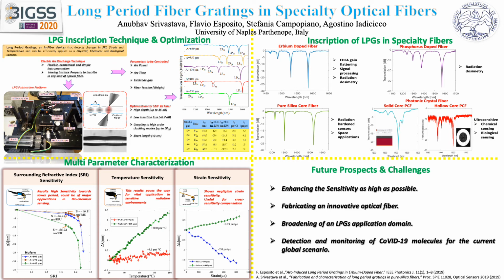Likewise, in temperature, you can see for photonic crystal fiber it is almost negligible, very little sensitivity, around plus 4.6 picometer, and for Nufern it is quite considerable, a significant sensitivity of around plus 30.0 picometer per degree Celsius. In strain, you can see it shows more or less negligible strain sensitivity, but it is very useful for cross sensitivity compensation. For Nufern around 445 micrometer grating period, we achieved around 0.73 picometer sensitivity, and for photonic crystal fiber it is minus 2.0 picometer, so it is almost negligible for both of them, so it can be used significantly for cross sensitivity compensation.